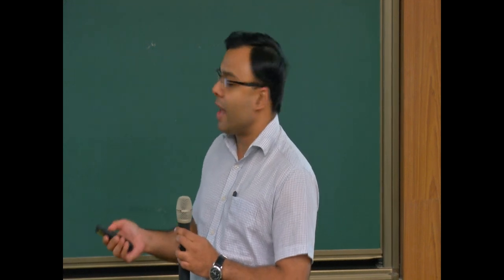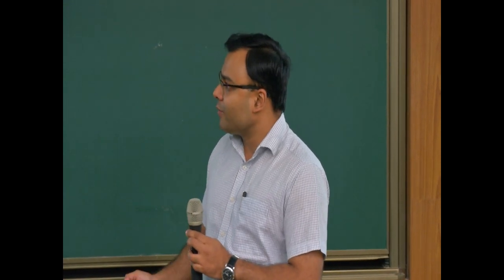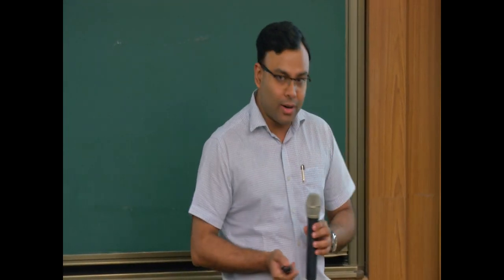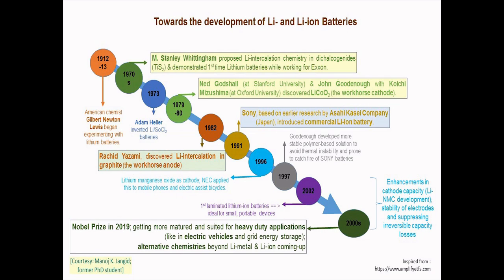So lithium from the anode side had to be replaced, and that is where Rachid Yazami, a Moroccan researcher, came into the picture, and he developed the anode material which could again intercalate the lithium in its lattice structure. He came up with the graphite intercalation, electrochemically intercalating lithium in the graphite and doing it reversibly. So then this led to the development of, I would say, almost the present generation lithium-ion cells having graphite as the anode and lithium cobalt oxide as the cathode.